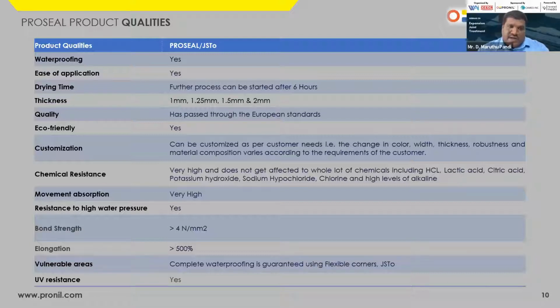And chemical resistance: all diluted chemicals as well as some of the concentrated ones, my product ProSeal is resistant to. The movement absorption is really very high, it will withstand water pressure, and it has a pull-out strength with the adhesive of 4 Newton per mm square. Elongation is high, UV resistant, and in some vulnerable areas where we cannot seal the joints, the tapes can also be used. We call it JSTO, joint sealing tape outdoor.